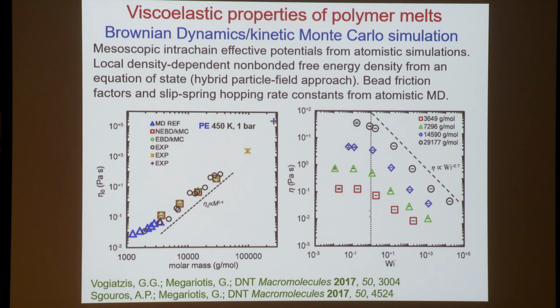For the non-bonded interactions, we introduce a local density-dependent non-bonded free energy density, which is based on an equation of state, in our case, the Sanchez and Lacombe in most of these calculations, which is consistent with the volumetric properties of the polymer. We also need some parameters for the dynamics. We need a friction factor for the beads. This we obtain from atomistic simulations by looking at self-diffusivity or Rouse modes, for example. And we also need a hopping rate constant for the hopping of the slip spring ends along the chains, and that can be related to the bead friction constant. So if one employs this mesoscopic approach, which is roughly 3 orders of magnitude faster than molecular dynamics, one can attempt the prediction of quantities such as the zero shear viscosity as a function of molar mass.